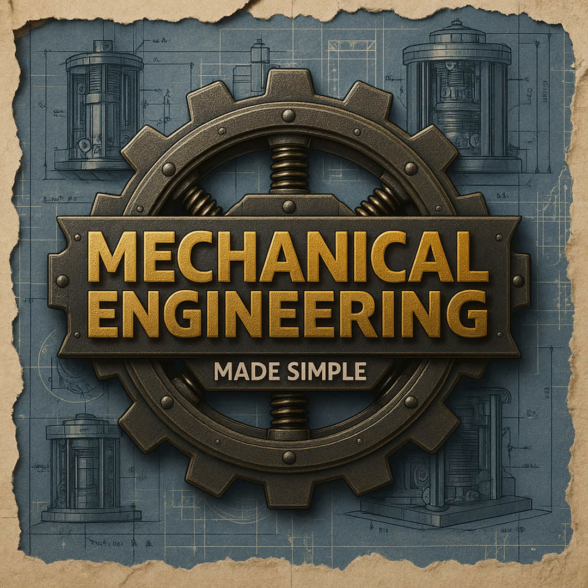So once the gear is cut and heat treated, you have to finish it. Why spend the extra time and money on grinding or honing? It's non-negotiable. Heat treatment gives you the strength, but it always introduces distortion. Always. And that distortion kills your accuracy and your surface finish. Which you need for load distribution and, I assume, for noise? Absolutely, for NVH performance. So finishing operations like grinding restore that precision.